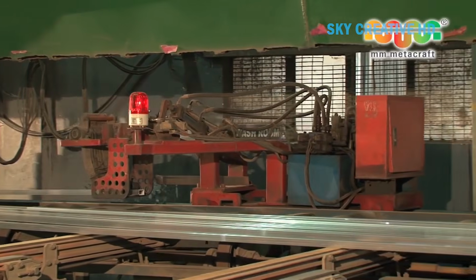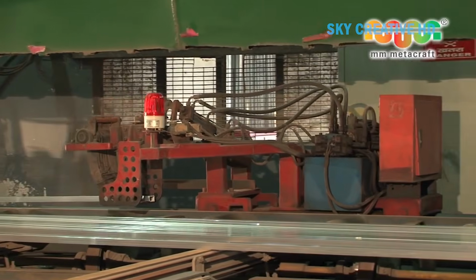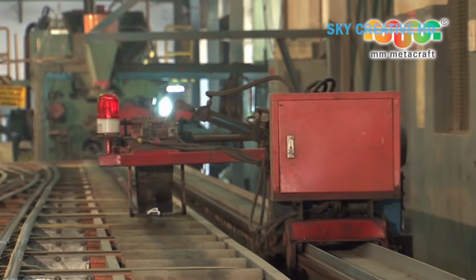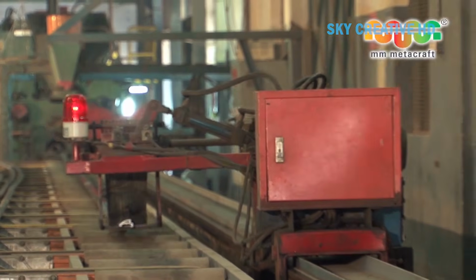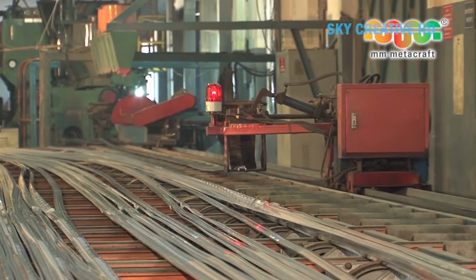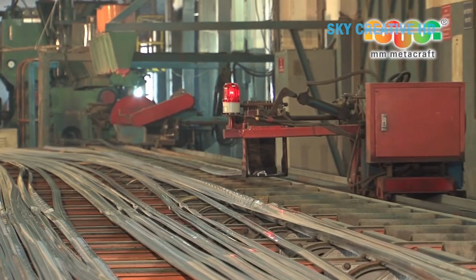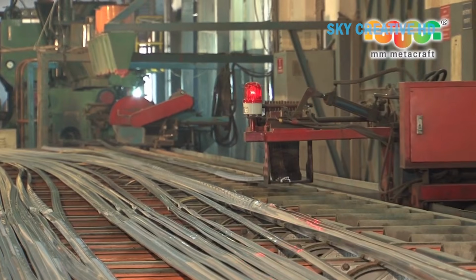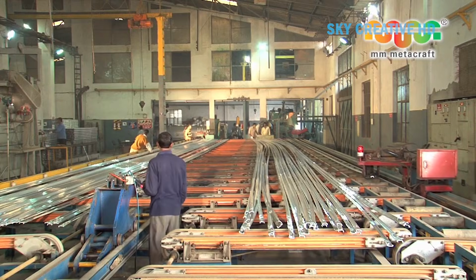the stretcher. The stretcher grips both ends of the profile and applies controlled tension, pulling it straight and relieving residual stresses that built up during extrusion. This step is what gives extruded aluminum its characteristic flatness and dimensional stability.